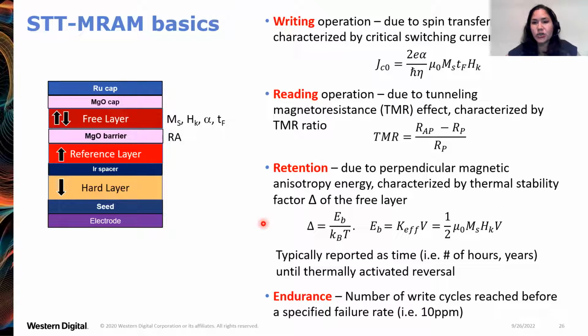Retention, this is due to the perpendicular magnetic anisotropy energy. So retention is how well can the free layer retain its written state up or down before the magnetization is lost to a thermally activated reversal. So this is characterized by the thermal stability factor delta, and it's usually reported in units of time. How many hours or how many years before you get flipping due to a thermally activated reversal.